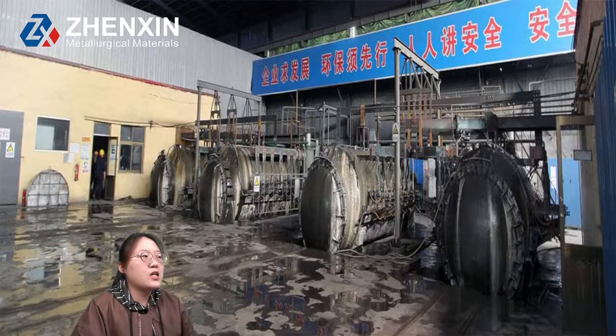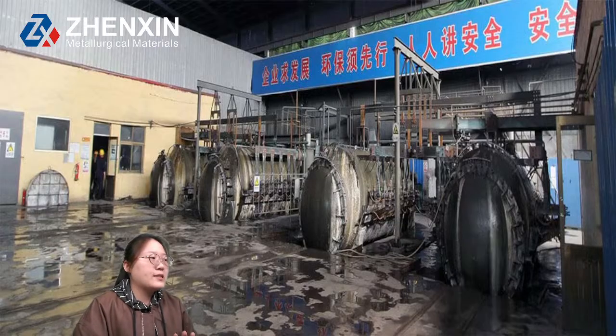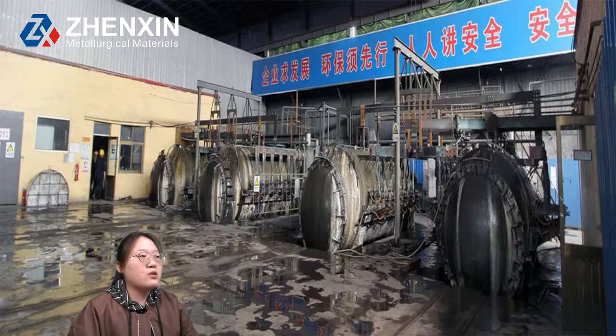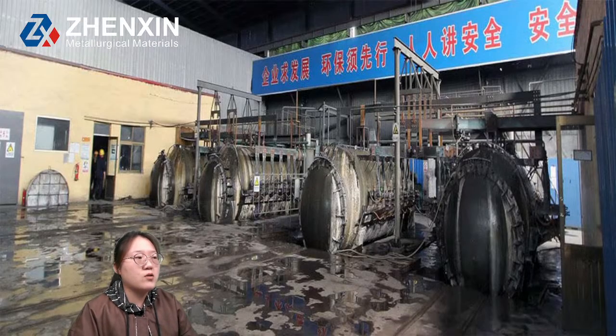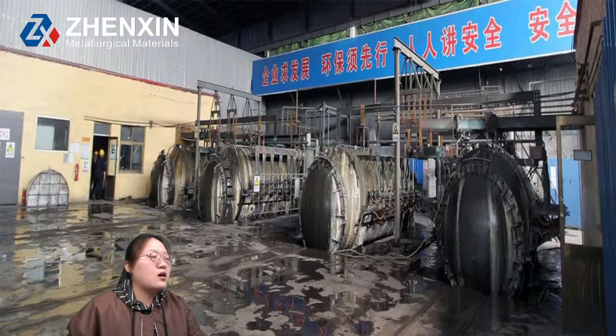For the specification of silicon barium calcium, for example, the silicon content higher than 50%, the barium lower than 15%, the calcium about 10%, and the carbon content about 0.4%. If you want the detailed silicon barium calcium specification, welcome to contact us to get a quotation for reference.